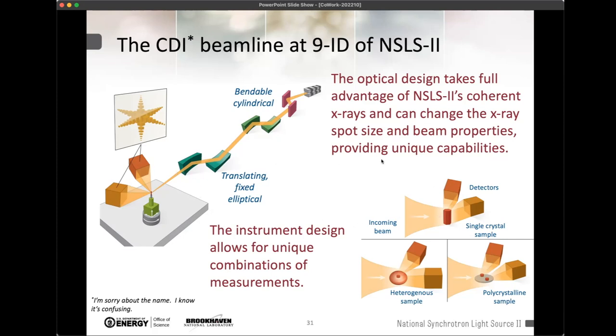This optical design allows us to tailor the properties of the beam coming onto the sample to best meet the needs of the experiment. The detector motion system coupled with two area detectors allows us to look at various kinds of samples. Three paradigms we're thinking about: first, a beam incident on a single crystal where you measure two different diffraction peaks using two detectors. Second, a heterogeneous sample where you measure forward scattering and Bragg reflections simultaneously, getting information about both amorphous and ordered components. Third, a polycrystalline sample where you measure diffraction peaks from different crystallites — if your instrumentation is good enough, possibly from neighboring grains to provide information about intergranular forces.